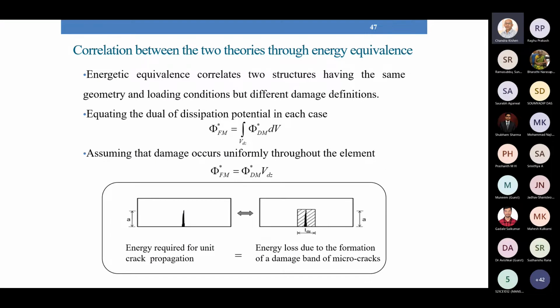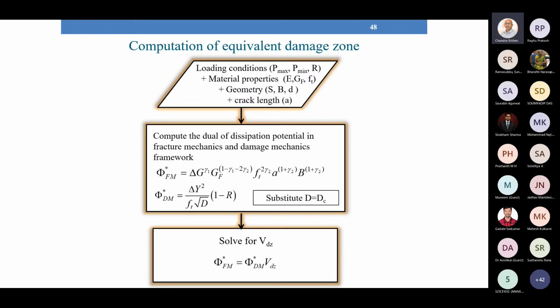Using both the thermodynamic potentials from fracture mechanics and damage mechanics, we could move from one theory to the other. That means, especially in finite element software, if we have software which uses discrete crack models and we know the damage zone, we can convert it into a discrete crack. Or alternatively, if we have software which uses continuum damage mechanics, we can convert it back to a discrete crack. We can use this energy equivalence. It will help us in moving from one theory to the other. That's the advantage of this.